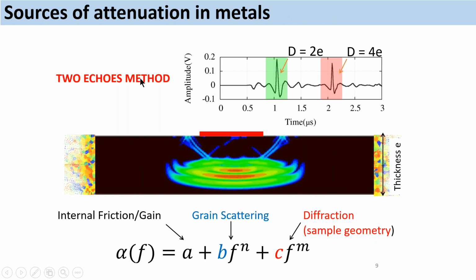So now the second parameter: what are the sources of the attenuation in metals? This is a little bit more tricky. There are several sources of attenuation, and we generally summarize those sources in three separate parts. The first one is the internal friction, A, which is generally considered weakly frequency dependent, so almost non-frequency dependent, at least in the range that we can acquire.